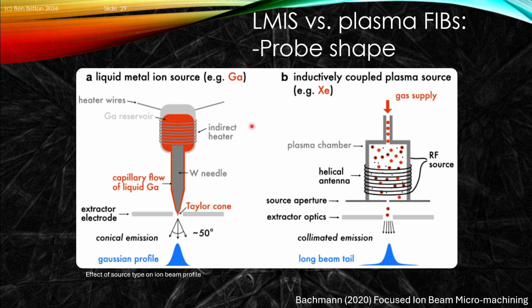Now you might ask yourself, well, okay, we've got these sources, why do we get the difference in the resolutions? And this is really controlled by the shape of the so-called virtual tip. So in the gallium source, we have the Taylor cone, which is that sort of 5 to 10 nanometer wet liquid cone, and then ions are emitted off with a conical probe. And we therefore produce a relatively narrow Gaussian profile. In contrast, when we have our ions being propelled through our extractor optics, we have a collimated emission, but the challenge here is that the collimated emission creates quite long so-called beam tails. And those beam tails will have a significant influence, as we'll see a bit later in our different applications.